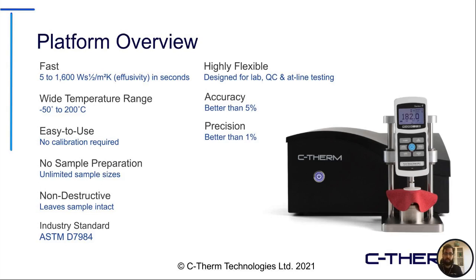And there's little to no destructive nature of this testing. This is simply a material being placed over top of the single-sided sensor. Accuracy, that means testing of known materials, is better than 5%, and precision, or the relative standard deviation of multiple tests, is better than 1% with this method.